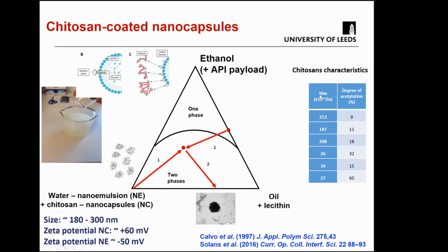We have tested different types of chitosans of varying molecular weights and degrees of acetylation. We see that regardless of the characteristics of the chitosan, it is always possible to coat these capsules with different types of chitosans, and that will determine their stability and some of their properties.